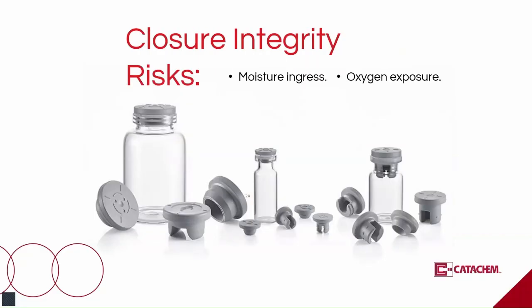Oxygen, moisture, and closure integrity. Even a perfect cycle can be undermined by packaging failures. If closure integrity is compromised, even microscopically, oxygen and moisture ingress can occur over months. That can change residual moisture, accelerate oxidation, and undermine stability. So we treat container closure selection as part of development, selecting vials and stoppers appropriate for the product and storage duration, ensuring crimping and stoppering are controlled, implementing inspection and, where appropriate, integrity testing strategies. This is one of the quiet variables that separates lab success from commercial reliability.